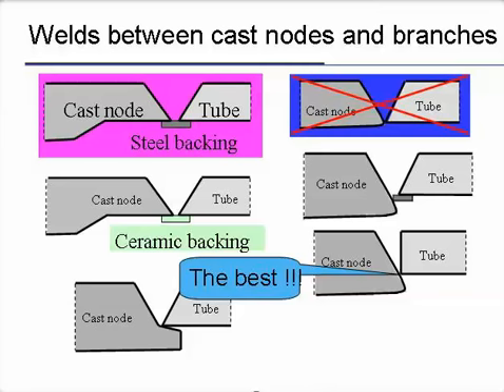So we made studies to see what would be the best solution to connect the cast node and the tube. Of course, you have this at the beginning, the tube and the cast node, which is not really possible because of tolerances problem. You can't do this solution here. Of course, you can do these kind of things where you have to machine here the cast node side and then put a steel or ceramic backing. But it's good, but it's very expensive to machine your cast nodes.